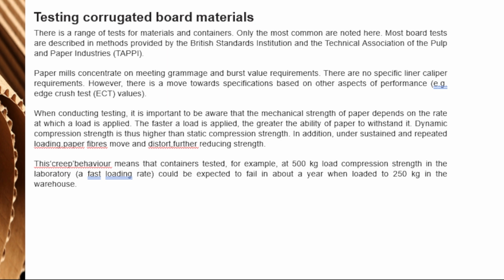When conducting testing, it is important to be aware the mechanical strength of paper depends on the rate at which its load is applied. The faster a load is applied, the greater the ability of paper to withstand it. Dynamic compression strength is thus higher than static compression strength. In addition, under sustained and repeated loading paper fibers move and distort, further reducing strength. The creep behavior means that a container tested, for example, at 500 kg load compression strength in the laboratory, at a fast loading rate could be expected to fail in about a year when loaded to 250 kgs in the warehouse.